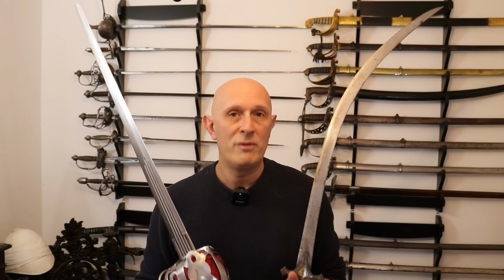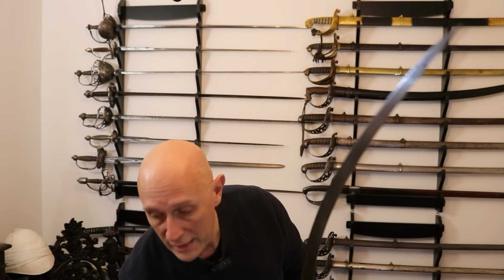You think about this from a fighting perspective. So this blade here, which is edge quenched, or a Japanese sword, could be as hard as 60 Rockwell at the edge, but really soft, like 15 or 20 at the back, and therefore if we suffer some kind of catastrophic failure, the worst that will happen to this blade is it will get bent.